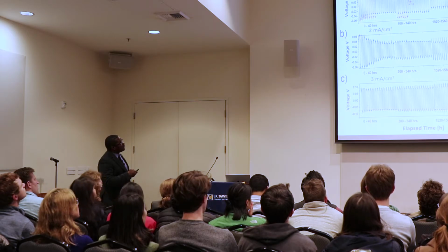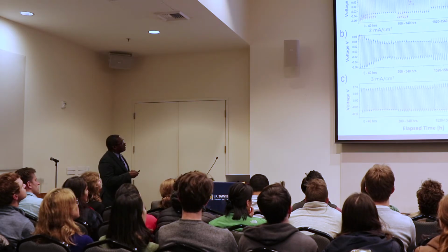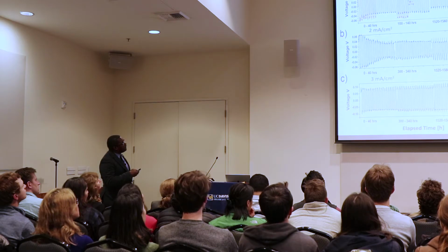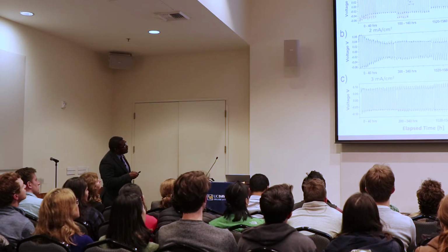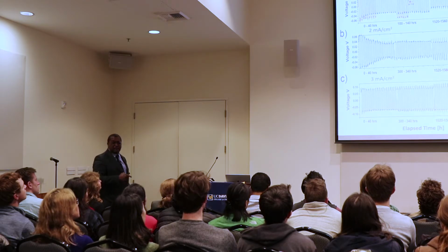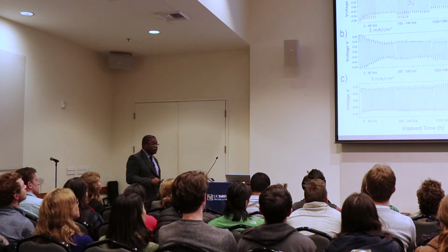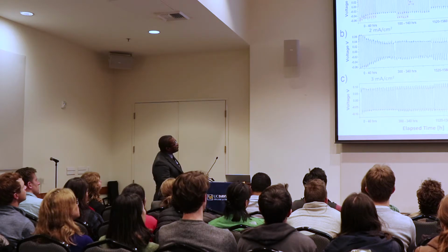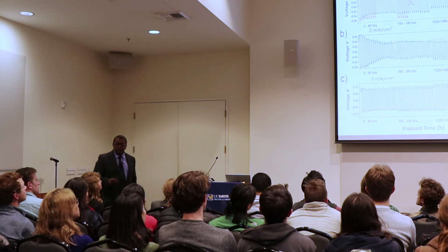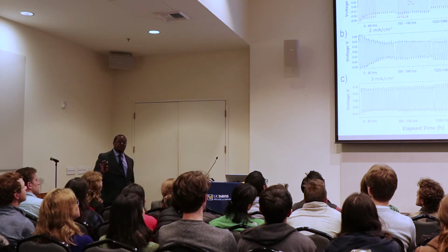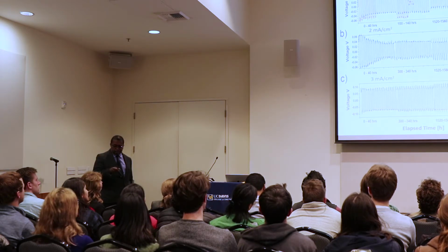At first, with just the normal electrolyte, we observe nice peak-to-peak values that are stable, and then they drop to 0. Then they pick up again, and then they drop to 0 and stay at 0 or close to 0. So roughly after about 150 hours, this cell is no good. It's completely shorted as expected.